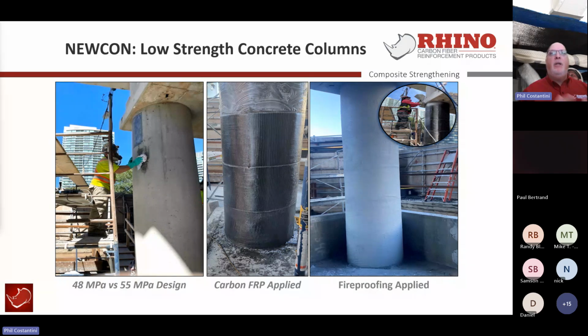And again, you can see we don't have to sandblast. I was talking about before about how strong columns are, the strength of the concrete, with just an easy surface prep. It could be hydroblasted. It could be just a low chemical washing of the concrete. We don't need to do more, unless it's very pitted and the concrete's very poor. If there's a void, then we'd have to repair it. In this case, because these columns on 11 floors, 20 of them on each floor, needed to be wrapped in order to get back to the original intent design of the strengthening of these columns.